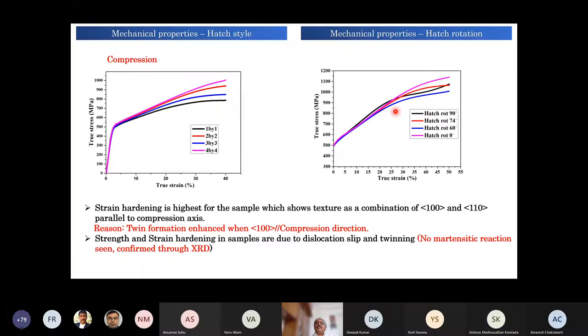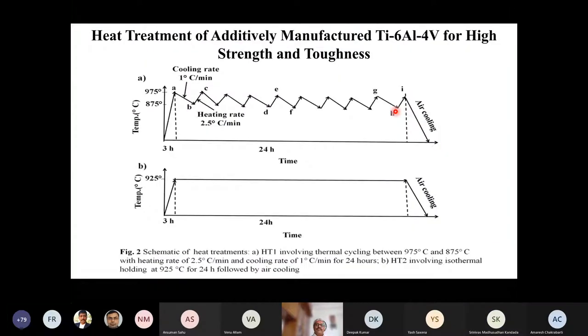Yes. So now the post-processing, where we have got a little bit of our claim to fame in our group. Now I am switching over to Ti-64, where we have systematically designed a heat treatment process. Normally, the normal heat treatment for titanium 6 aluminium 4 vanadium should be like this. But for additively manufactured products, we have used a cyclic processing strategy.